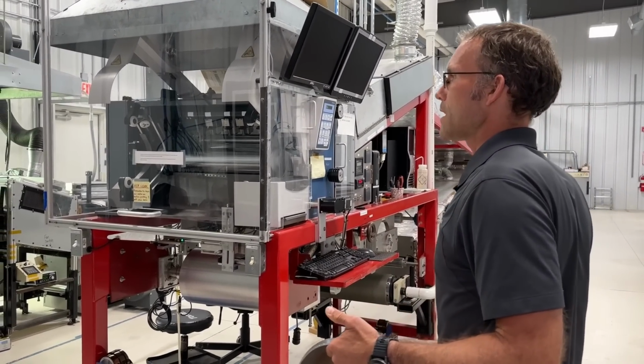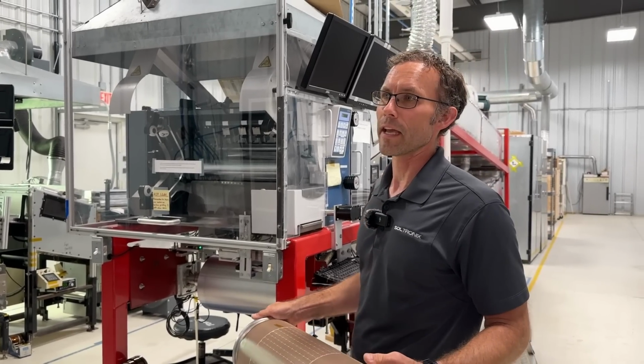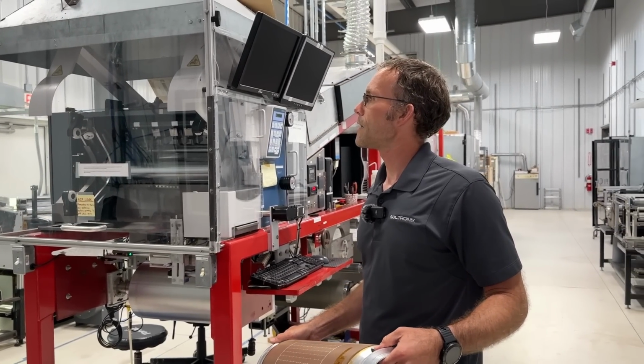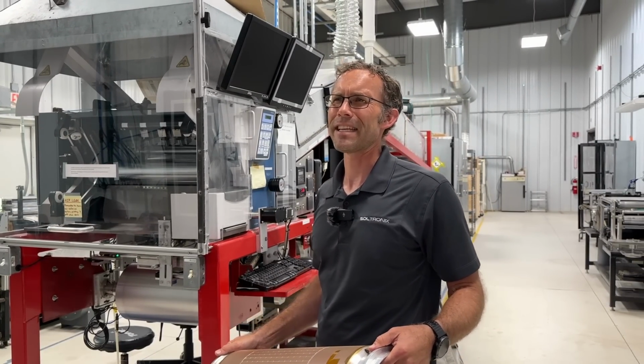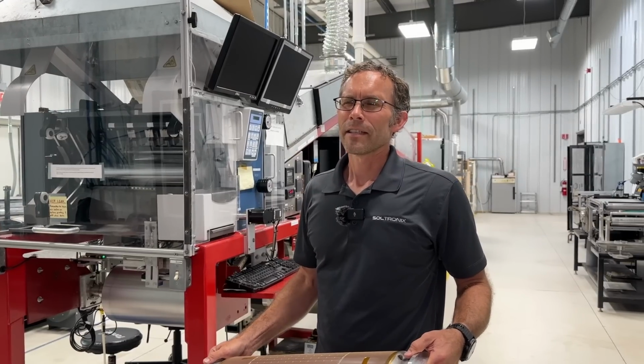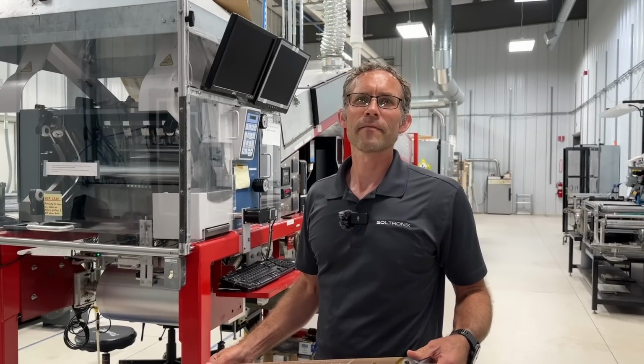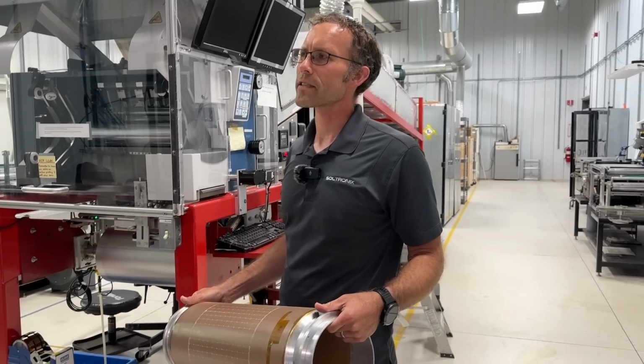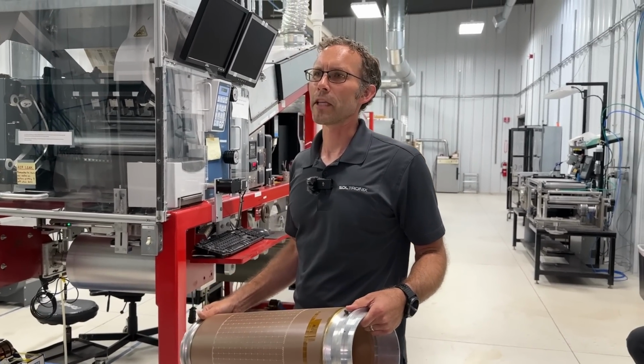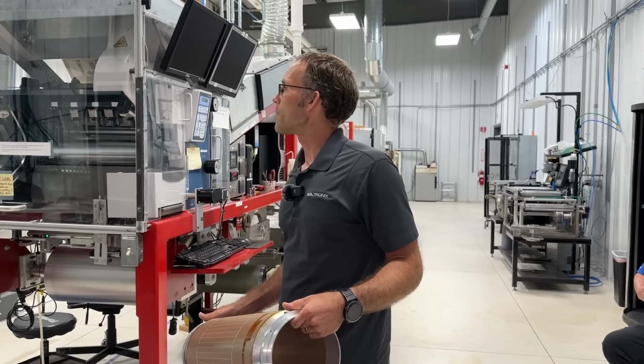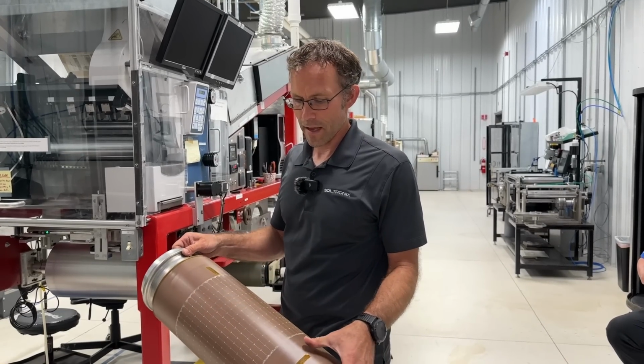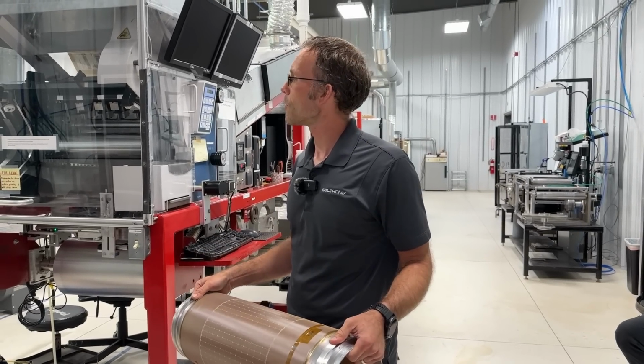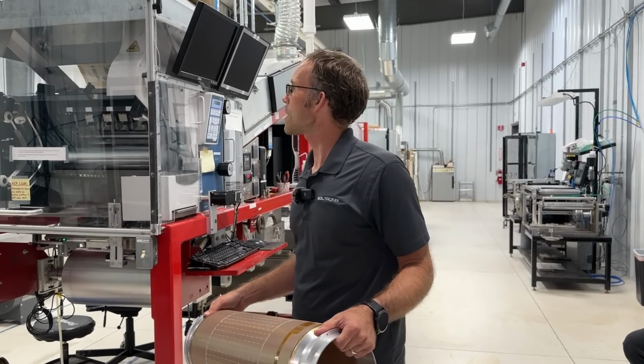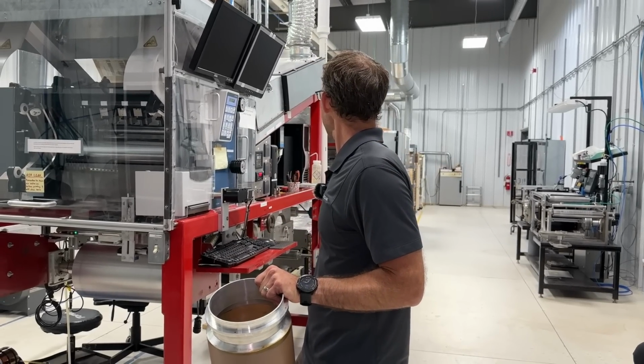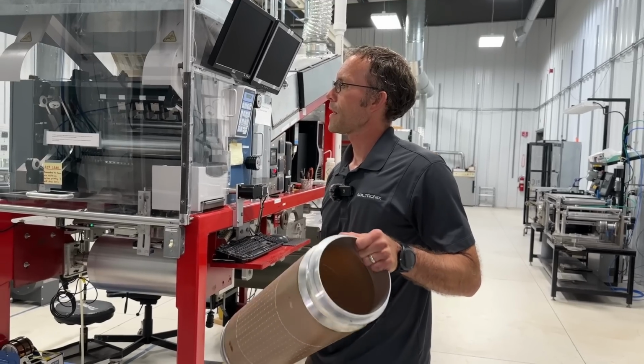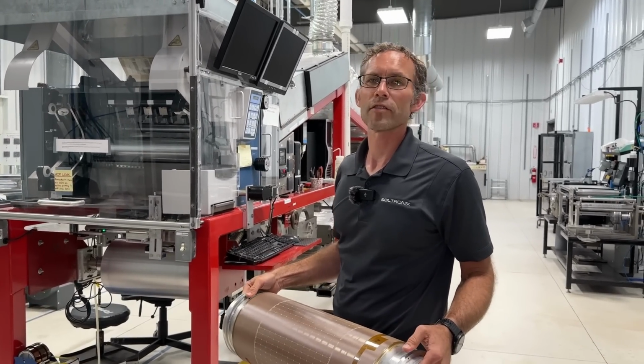The silver print is a kind of a standard silver flake ink. It has about like a D90 of, I think, 15 microns for a flake size. The conductivity is somewhere around 10 milliohms per square. And it acts as the top grid then that's on the material. And so it's a thermal cure, not a UV cure. So we have IR ovens on the back of both of the systems, and the IR heaters will cure this ink and get it in place.